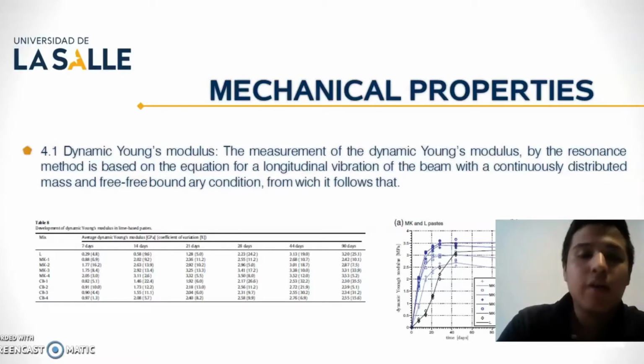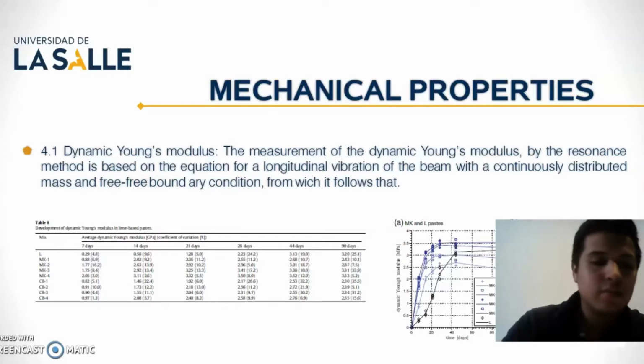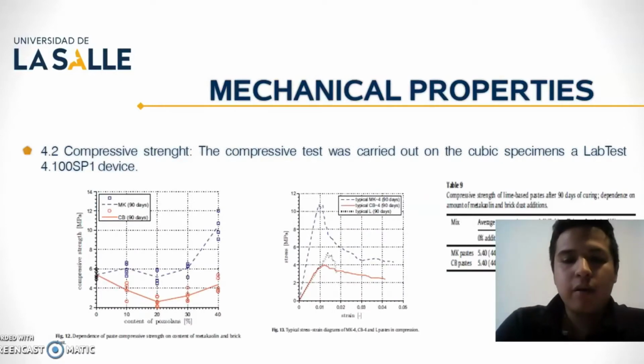Our measurement agreed with the study of Vega and Carvalho, who found that the stiffness in the case of lime metakaolin mortar decreased from the age of 28 days to the age of 90 days. The shrinkage-induced cracking around aggregates in poor lime mortars without addition of pozzolan is responsible for the increased permeability and reduced mechanical strength rather than the weaker matrix.